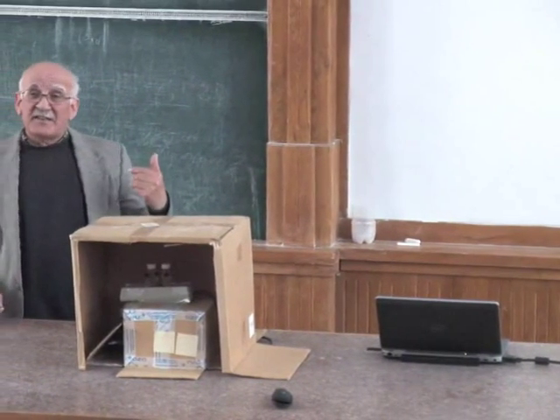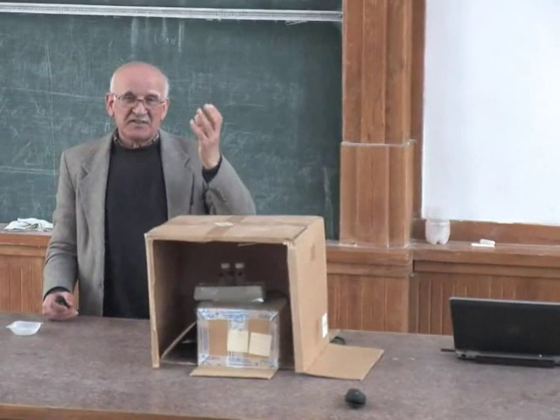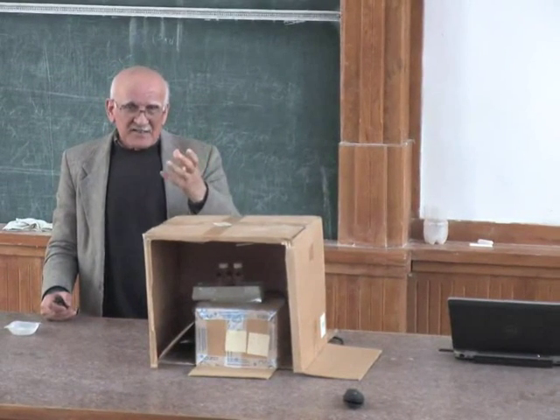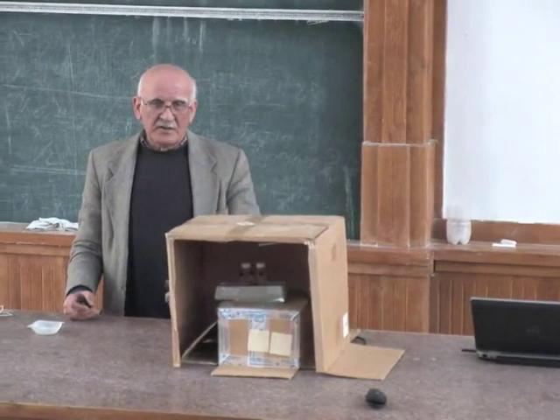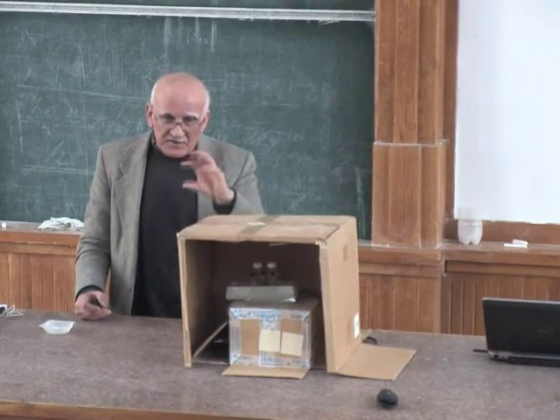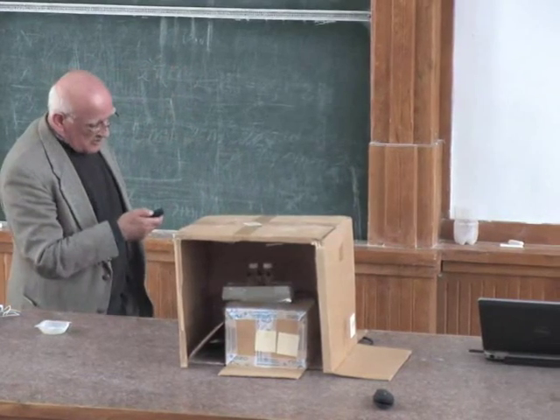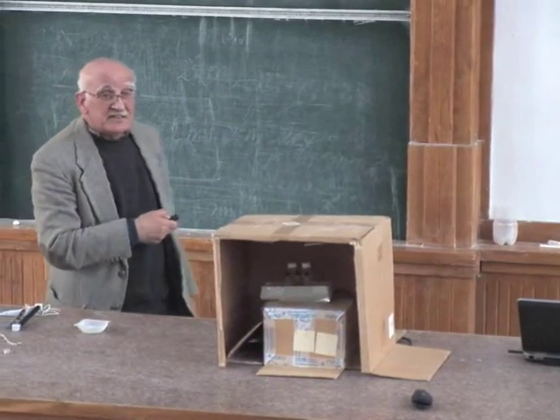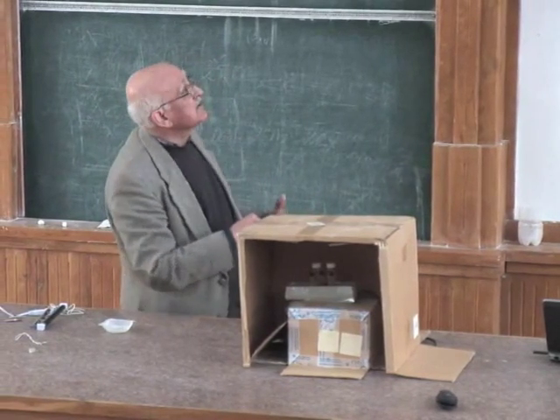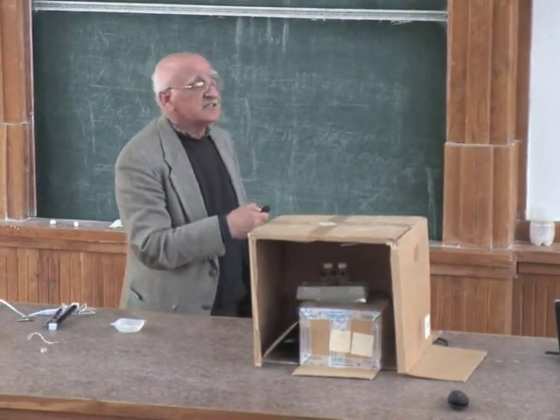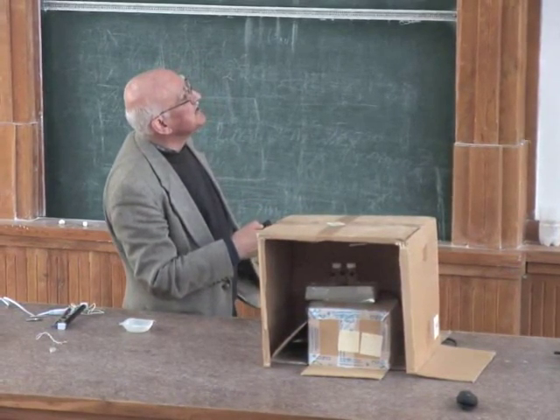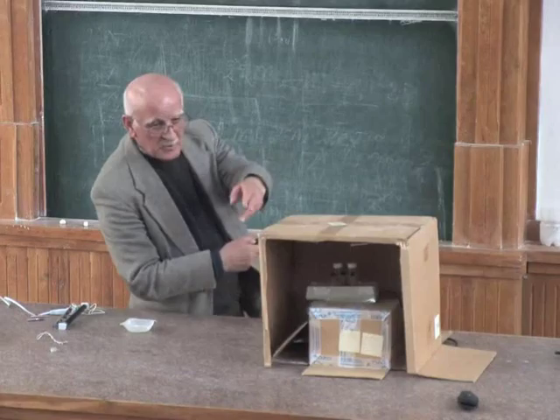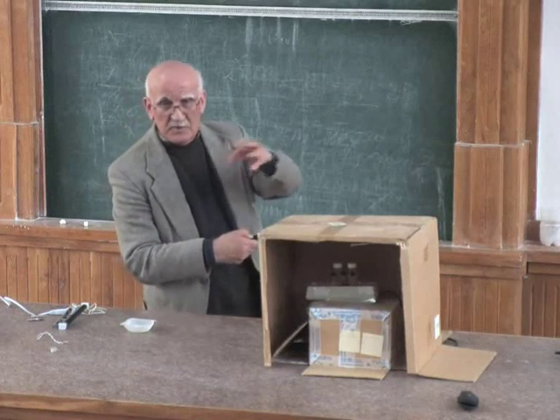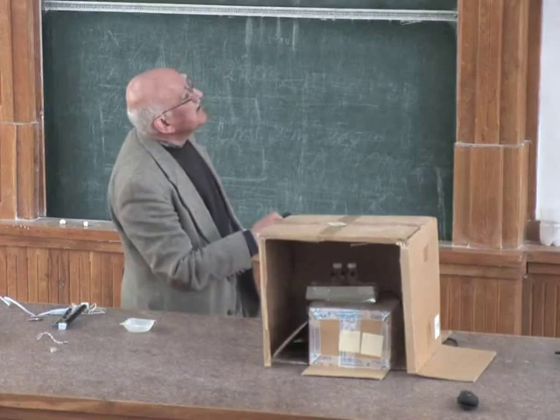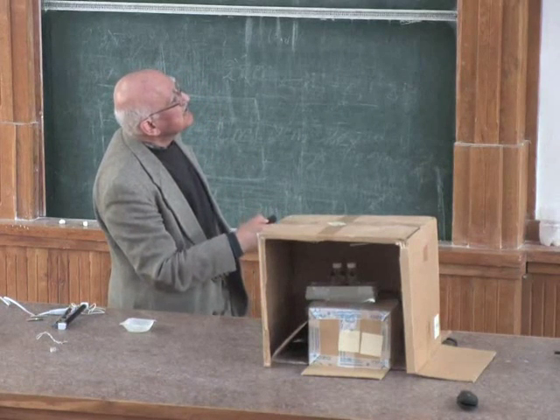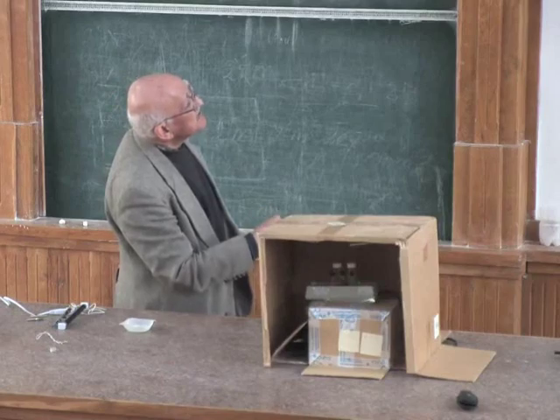Here, which is the same idea, remember in E&M, electricity and magnetism, the capacitance of an object is proportional to the radius of the sphere. And so with the nanoparticles, they have a big capacitance, so they can store a lot of charge. That means you can make a better capacitor, a supercapacitor. So what we've done, here's a brush. And we mix the nanoparticles in this liquid with some polymer or something, and we painted a very thin plastic sheet. On this side, turn it around and do the same.